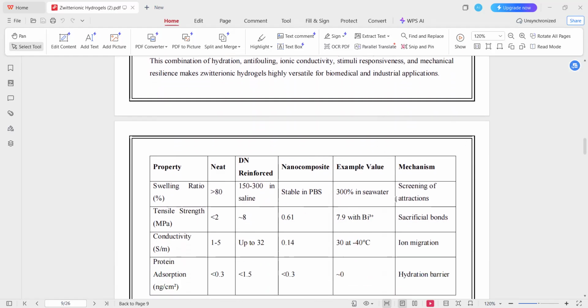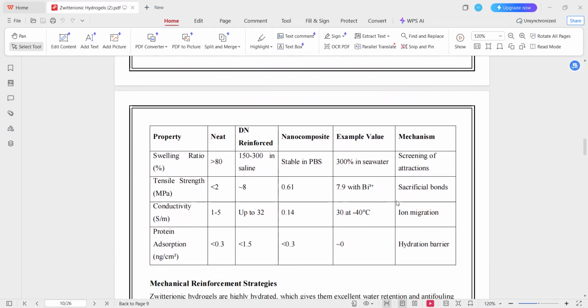The table here compares the neat, double network reinforced, and nanocomposite Zwitterionic hydrogels in terms of swelling, mechanical strength, conductivity, and anti-fouling performance, along with representative values. Neat hydrogels show high swelling above 80%, but very low tensile strength of 2 megapascal. After double network reinforcement, swelling remains high at about 150 to 300% even in the saline environment, while the tensile strength increases dramatically to around 8 megapascal due to sacrificial bond mechanisms.